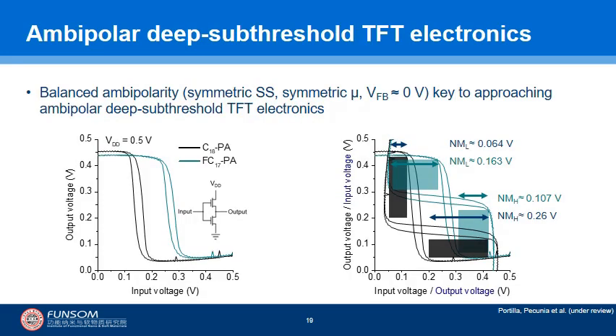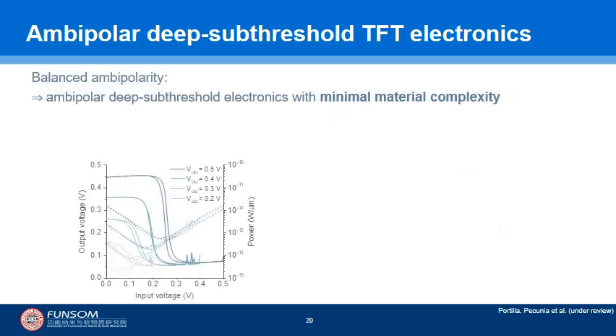Going back to our deep subthreshold ambipolar inverters, the flatband voltage shift achieved with the fluorinated SAM molecule did have the desired outcome. Inverters did acquire a more symmetric characteristic, and this was thanks to their more balanced ambipolarity, which in fact does not only involve their flatband voltage, but also their mobility and subthreshold slope. And this enabled, firstly, much larger noise margins at VDD equals 0.5 volts, as you can see from the plot here. Balanced ambipolarity, that is symmetric subthreshold slope and mobility and flatband voltage around 0, then enabled us to establish the paradigm of ambipolar deep subthreshold TFT electronics.